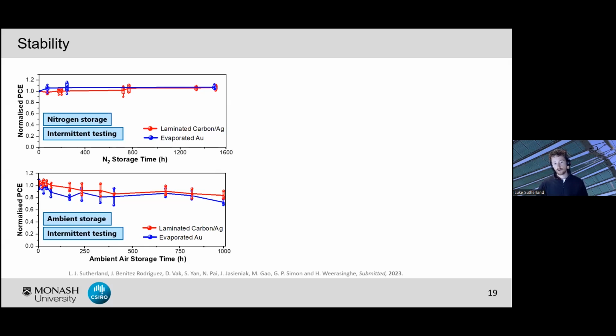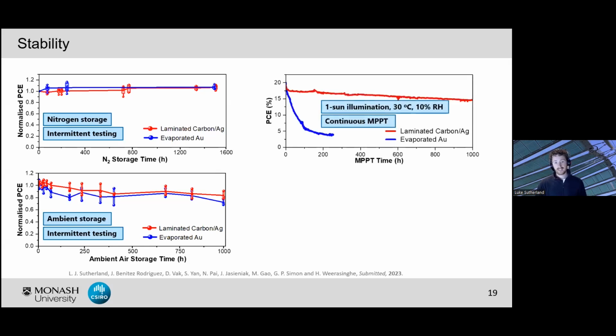However, once we progress to continuous illumination, accelerated operational conditions, that's where we were able to see a significant difference in the stability performance. So this is in a low humidity environment, 10% relative humidity, 30 degrees, and continuous MPP tracking. Over 1,000 hours, we can clearly see that the evaporated gold cell rapidly degraded. Within 10, 20 hours, it had lost a significant amount of its efficiency, and after 200 hours, it had dropped substantially.